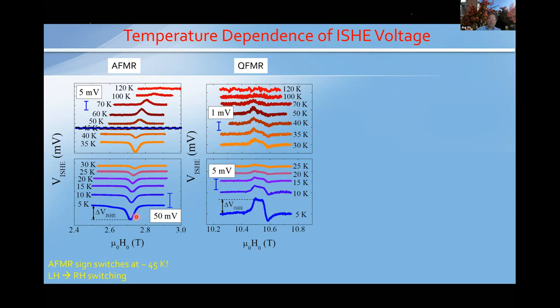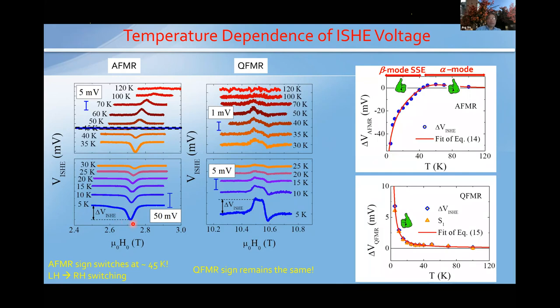So we plot this peak position at resonance. For antiferromagnetic resonance, we have this overall temperature dependence. As we cross 45 Kelvin, going below 45, you notice the scale change, right? 50 millivolts here, 5 millivolts there. So there's a huge rapid increase in the magnitude at low temperature in this beta mode. This is the quasi-ferromagnetic mode. It also has an enhanced signal at low temperature.